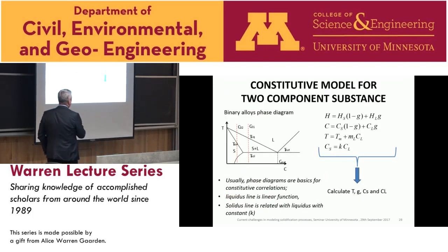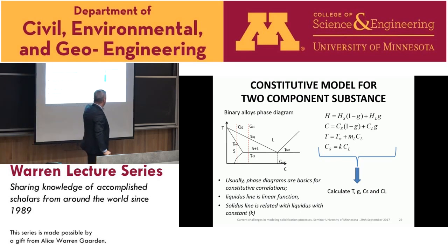And the constitutive model for alloys is usually the phase diagram. These phase diagrams give you information about the slopes of the liquid line and solid line, and about partitioning, how much the concentration of solid is less than the concentration of liquid, and so on. So we use this model. As you can see, H and C are input parameters. And from these equations, we calculate the temperature, G, CS, and CL.